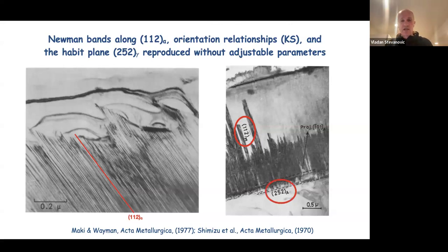So to my understanding of the field, I'm not exactly a metallurgist, but I sit in a metallurgy department. This is the first model that does not include any adjustable parameters or experimental information, except the two lattice constants, that produces almost all frequently observed experimental facts about this phase transformation, which was a very nice and somewhat unexpected result, and all a consequence of minimizing the displacements of atoms without including periodicity.